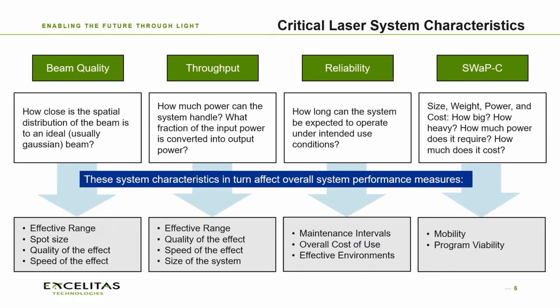Now the laser characteristics for these applications that are typically the most critical as they relate to the optical specifications are the beam quality, throughput, reliability, and what's typically referred to as SWaP-C, which is size, weight, power, and cost. Now, the beam quality is typically the distribution of the beam, and that gets to what the range of the laser is going to be, what the spot size can be, how high quality that spot is going to be, and how quickly it's going to act. Because usually a smaller spot is going to have a faster effect than a larger spot.